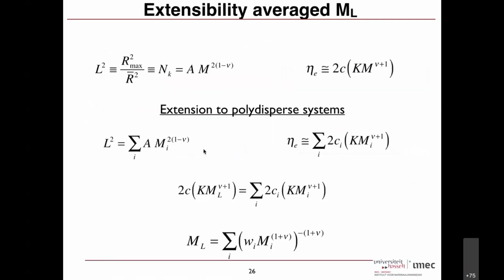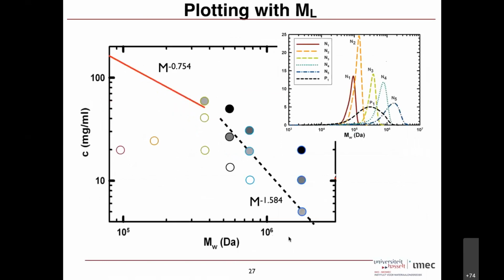Then we have to define something called the extensibility average molecular weight. Again, this is algebra, I'll not go into detail. Finally, we get this. How much the molecule can extend is basically the extensibility molecular weight. Effectively, what is the molecular weight? It goes as some kind of weight fraction times the molecular weight to the power of some kind of solvent quality. So you plot concentration as a function of normalized length of the molecule, and that's how the curve looks.